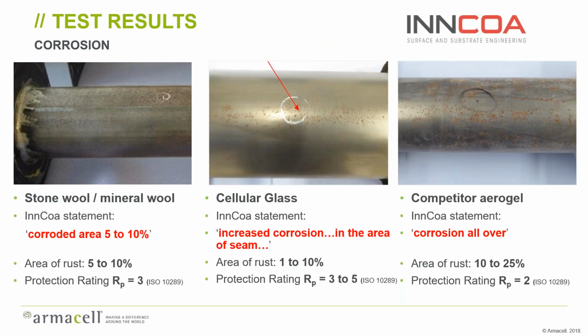On the left, there's stone wool or mineral wool. And InnCoa's statement was that there was 5 to 10% corrosion across that pipe, and they gave it a protection rating of 3. Their protection ratings, which are according to an international standard, range from 0 to 10, where 0 would be the worst and 10 would be the best.